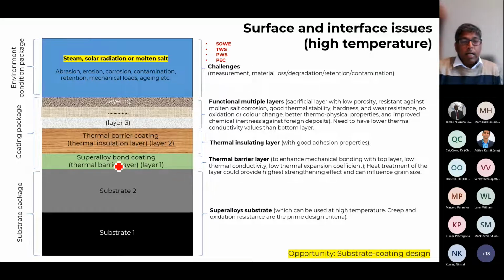So it is a hypothesis here, a simple schematic diagram where I'm suggesting that you have a substrate. Can we take another type of substrate or have a functional substrate? Normally you select superalloy materials which are used at high temperature, which can resist creep and oxidation. And then you can have a bond layer, a thermal barrier layer, and this is to enhance mechanical bonding between the underlying substrate and the top layer. It can have a low thermal conductivity, low thermal expansion coefficient, and so on. Then you can have another layer, which is thermal insulating, where this end and this end should have good adhesion properties. So that is going into the package of coating.